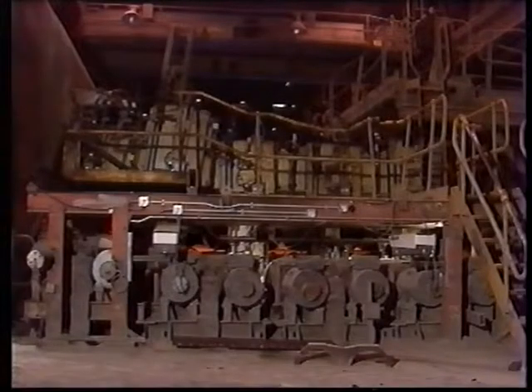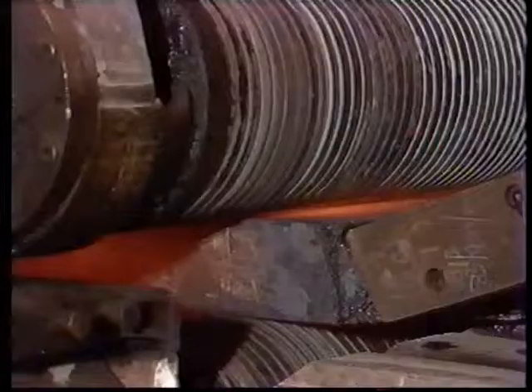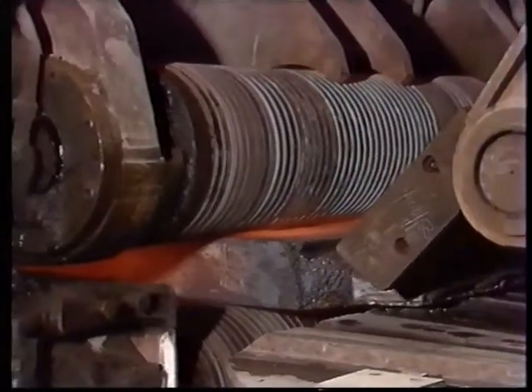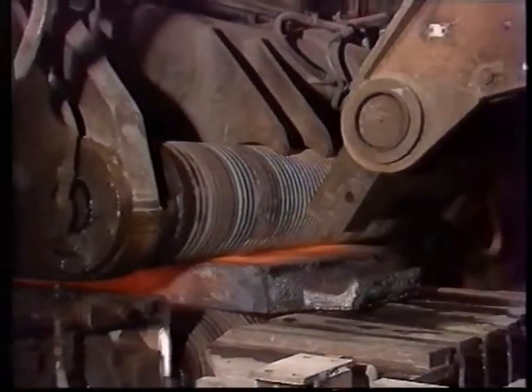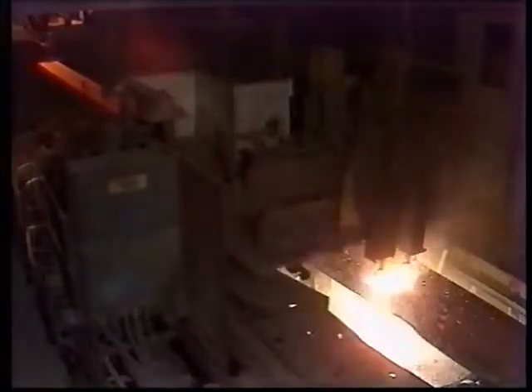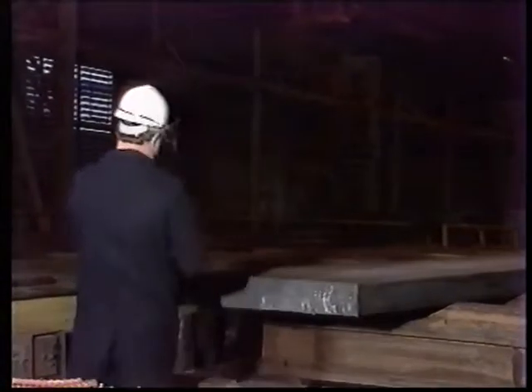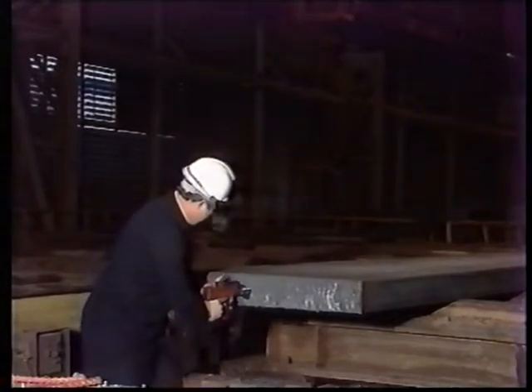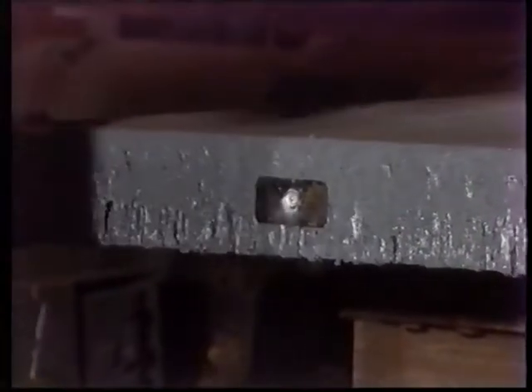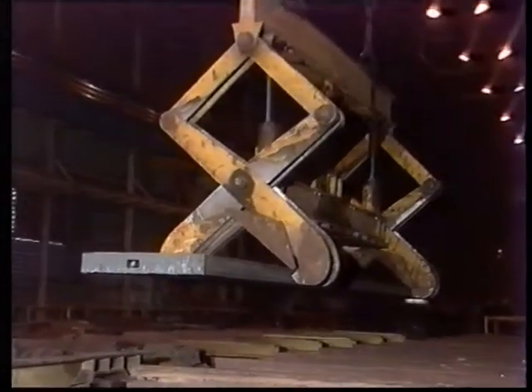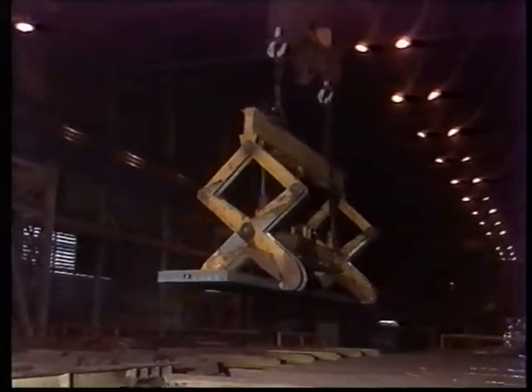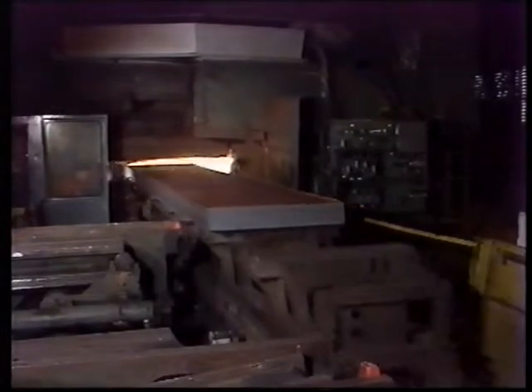When the slab of stainless steel emerges from the spray chamber and into the straightener, solidification is complete. As the new slab leaves the straightener, the dummy bar disconnects automatically, and the slab is then cut to length by a flame cut-off machine to a predetermined cutting plan. The run-out of the continuous casting machine takes slabs into the slab processing bay, where they're tagged for identification purposes and are cooled either above ground or in a temperature-controlled pit, depending on the type of material produced.